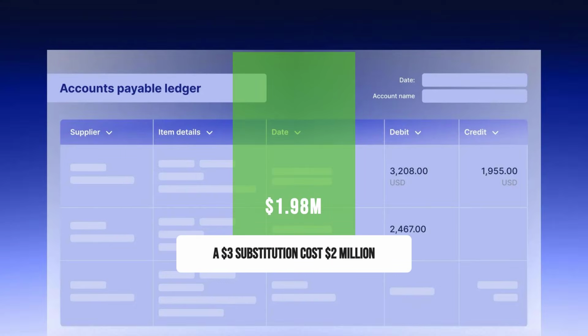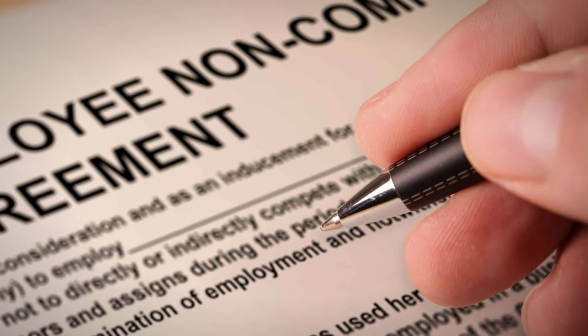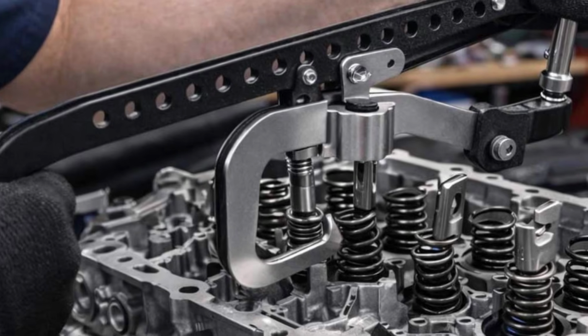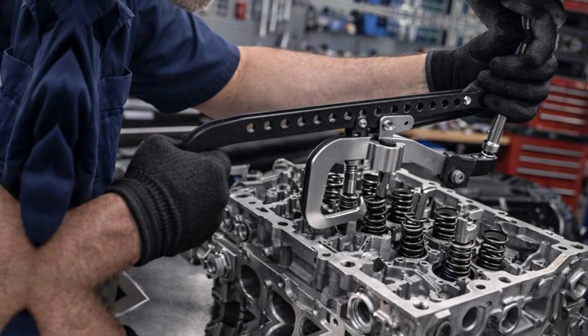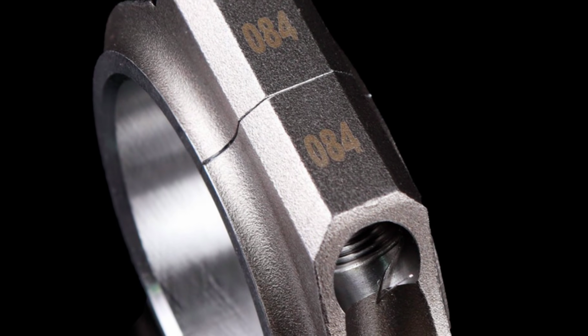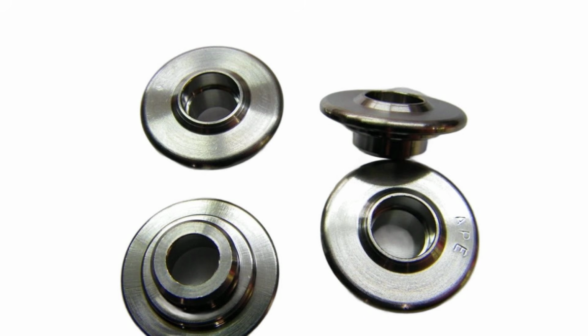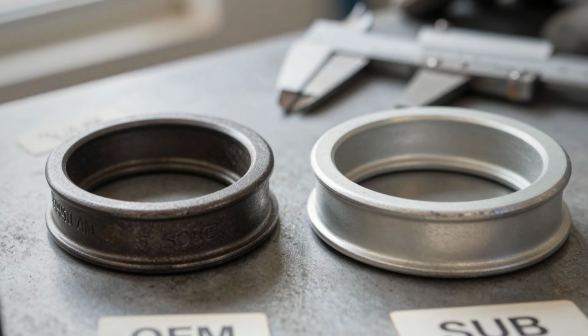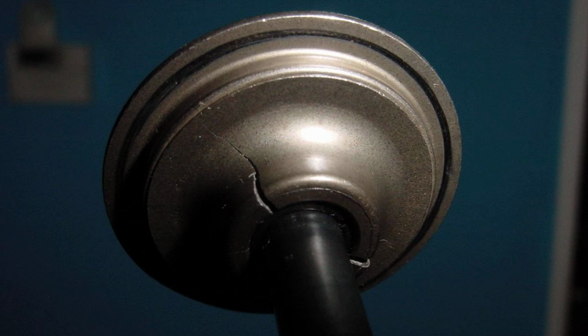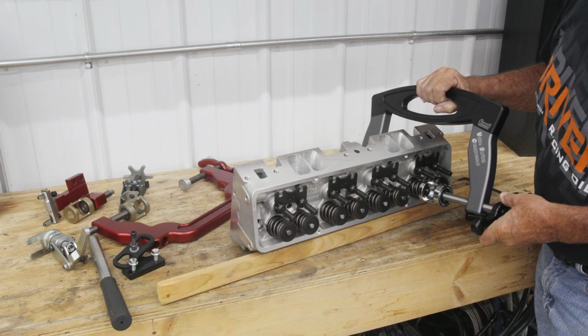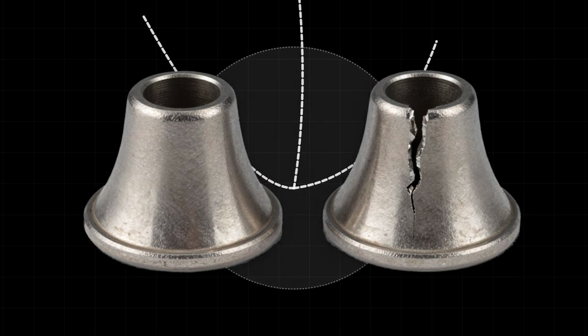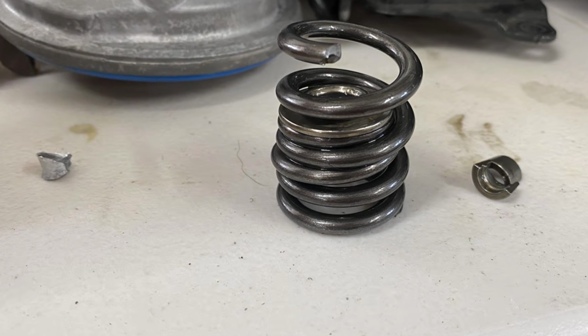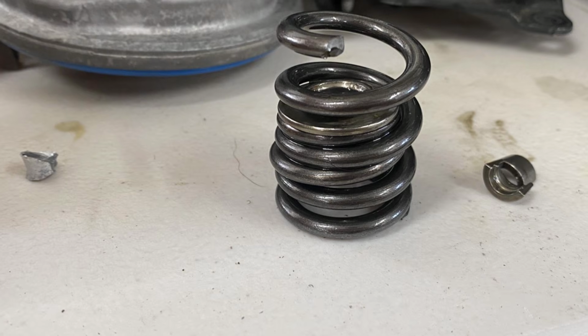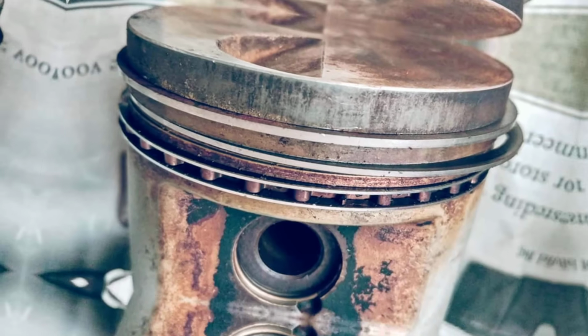The procurement record shows the cost saving, $3 per retainer, a savings of 40% over the OEM part. Management signed off. The retainer was installed untested into a prime mover designed to restrain a 60-pound forged piston moving at 30 meters per second. The interference design offers no margin. The retainer lip, under-specified and under-hardened, cracks on the second maintenance cycle. The valve keeper, now unsupported, is forced to absorb the entire spring load and piston impact. The result is deterministic. The keeper shears at the groove, the valve drops, and the piston is obliterated.